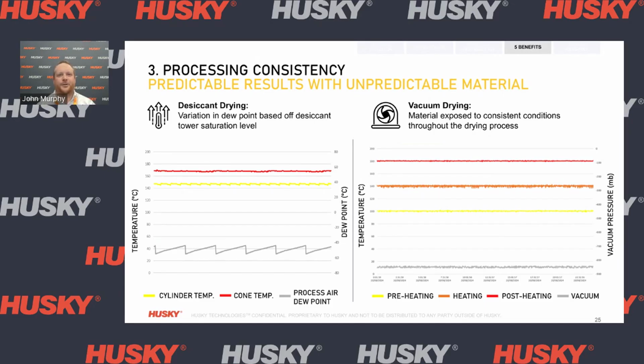On the left-hand side of the screen, you can see a process screen of a desiccant drying system showing the cylinder and cone temperatures, as well as the process air dew point when switching desiccant towers. What I'd like to show you is that when we look at the temperatures, the cylinder temperature and the cone temperature, we see a very stable process. And as well, when we look at the process air dew point, it is certainly a stable process at an acceptable level, but we do see those small fluctuations when changing the desiccant towers.